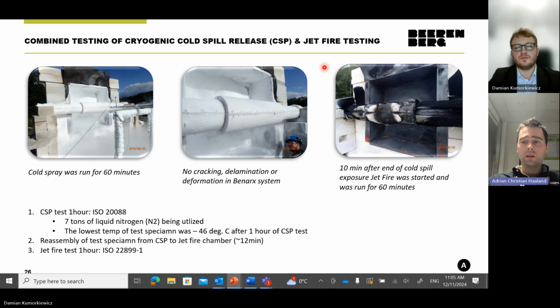Cryogenic testing is something that started to come up around 2016-17, with the new ISO 20088 being published after some time. As I mentioned briefly, this is a 3-part standard. You can do the jet exposure, the fog exposure, or the immersion type, where you actually immerse the panel system itself under liquid nitrogen. You expose it to 1 hour of liquid nitrogen, and then after the test, you go straight into jet fire or even explosion testing.